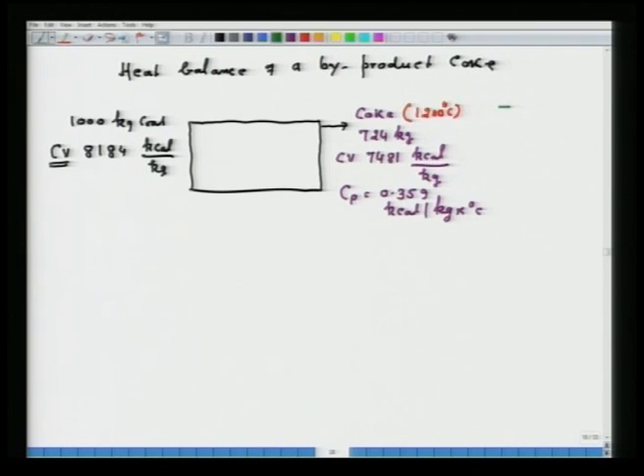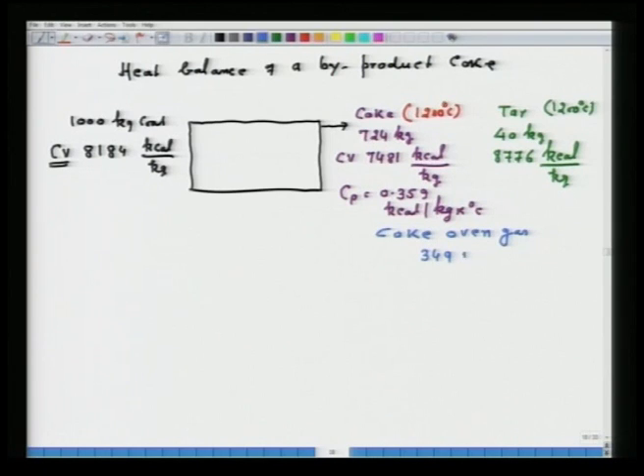Another product as we have shown there is tar, which amount is 40 kg and its calorific value is 8776 kilocalorie per kg. It is also discharged at 1200 degrees Celsius. Then another product is coke oven gas, whose amount was 349 meter cube, calorific value 103 into 10 to the power 3 kilocalorie per kg mole, and its density is 0.44 kilogram per meter cube.